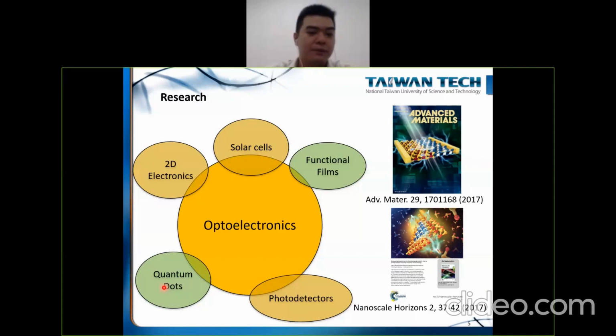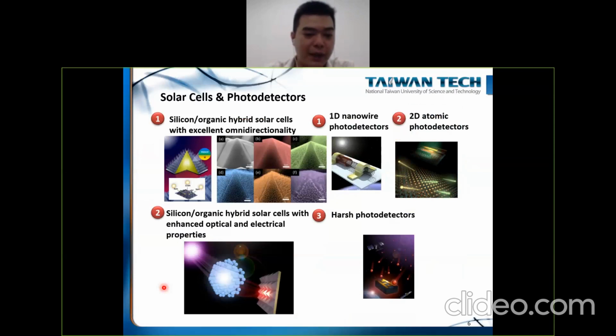And this was also from my past, so I'm going to just briefly introduce. I work on the structural engineering of silicon solar cells, for example, fabricating nanostructures on top of micropyramids in order to improve the light harvesting or the omnidirectionality of the solar cells. Okay, we also mixed 2D quantum dots, such as graphene quantum dots, with organic solutions such as PEDOT:PSS to fabricate these hybrid solar cells with enhanced optical and electrical properties.